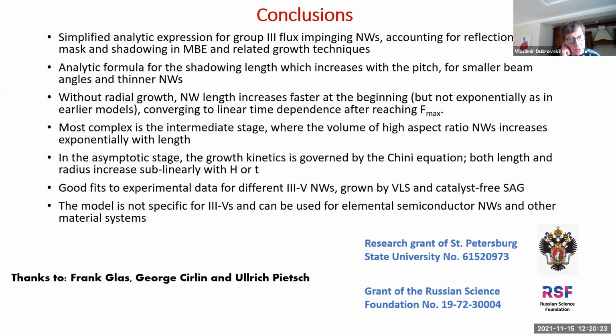And in the asymptotic stage, both length and radius increase sublinearly with time. We have obtained good fits to different experimental data. And I think the model is not specific for III-Vs and can also be used for elemental semiconductors or in other material systems, where the major effects are the reflection from the mask surface and shadowing, which is always present in MBE. And maybe the last conclusion is that the asymptotic stage, where the surface is blocked by shadowing, is exactly the same for reflecting or sticky substrates. So it doesn't matter anymore because there is no more substrate in play.